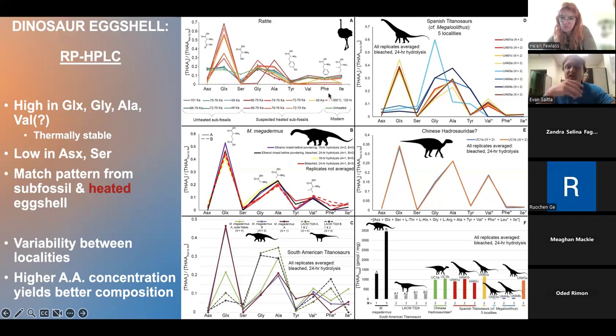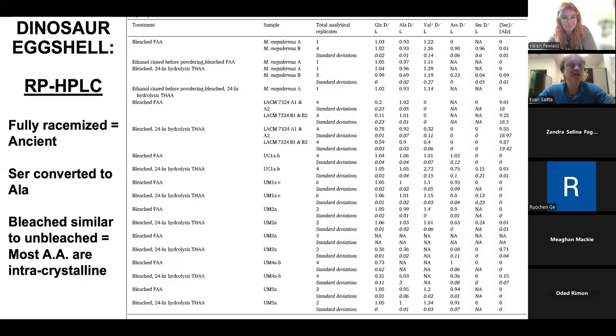And so when these results first got printed off of the chromatograph, Kirsty saw them and started shouting and jumping up and down. It was very exciting because this is exactly the sort of profile you would expect from a very, very ancient eggshell, essentially at the very end of that diagenetic continuum of degradation of eggshell proteins. Now, there is variability between the different localities. So you can see some of these titanosaurs do not give as clean of a result. And this appears to correlate with the amount of amino acids overall within the sample. So the more amino acids that are preserved in the dinosaur eggshell, the better the profile is to that which would be expected from an ancient eggshell, which I suppose is not too unexpected.